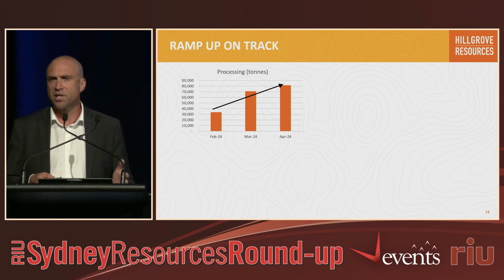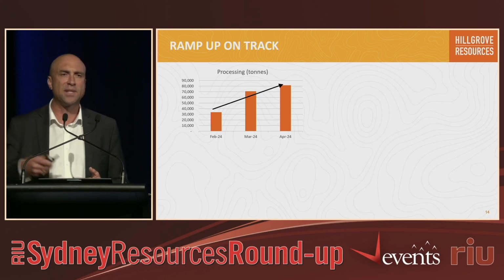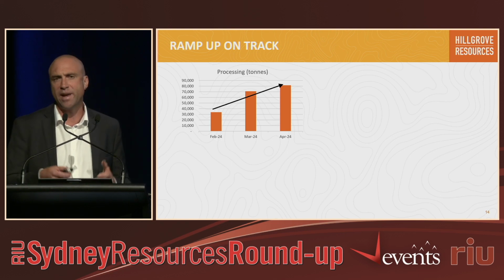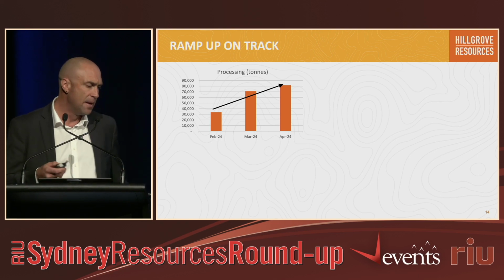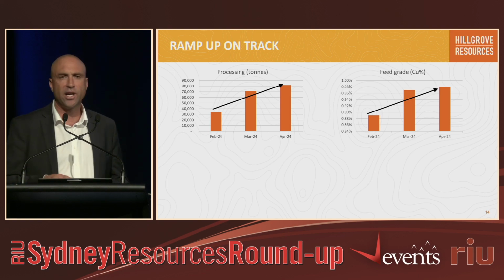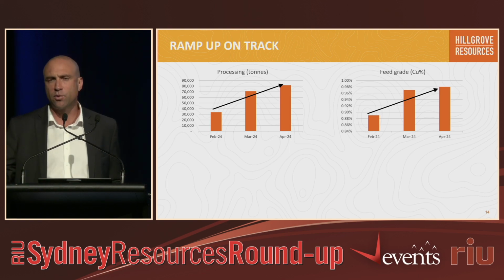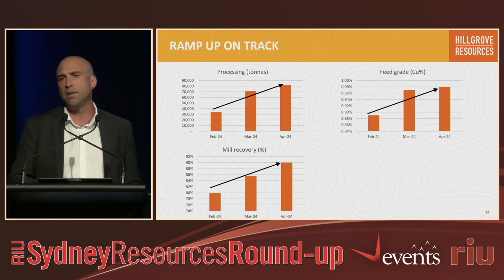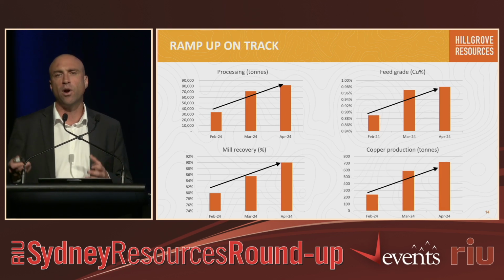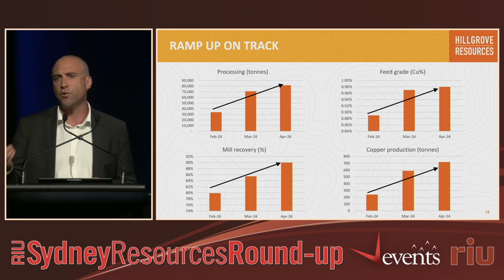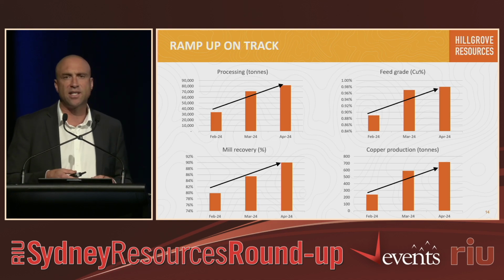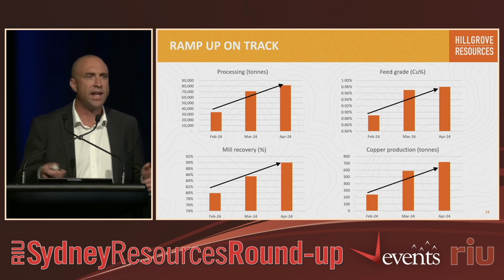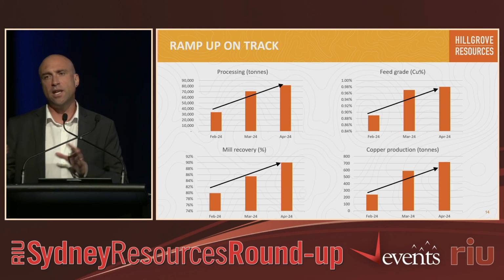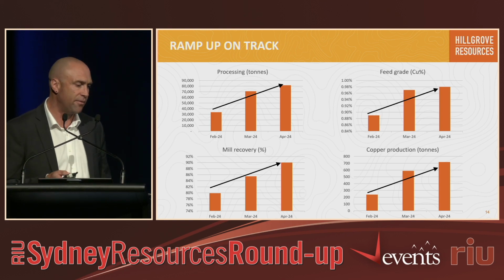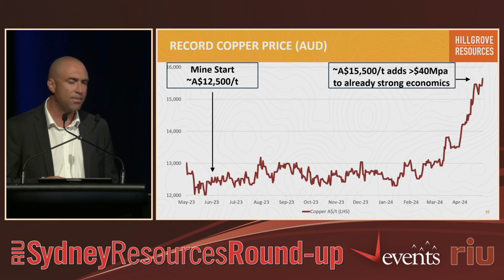We started off a relatively modest campaign, about 30,000 tonnes. That's now pulled up to 80 and will continue to grow towards about 120 as our steady state. But all the metrics are heading in the right direction. Feed grade's gone from about 0.88 up to around 1%, recovery from about 80% to 90%, and all this has culminated into an increasing metal profile from about 240 metal tonnes. It's now tripled in those 3 months to about 720, and we're on target in May to knock that out of the park once again. So everything is on track, and we're well on our way to delivering to the mine plan.